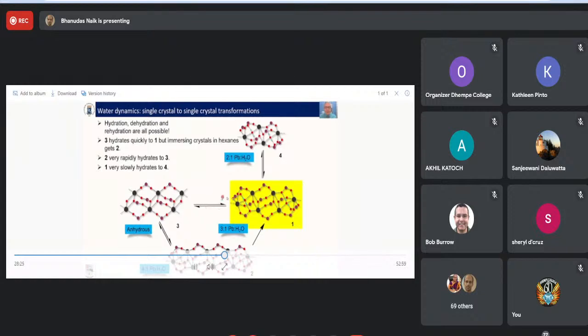In this compound, you can dehydrate 3 and you get the anhydrous compound. And if you're really, really careful when you hydrate it, you can manage to get crystals of this compound. So this is a single crystal transformation. We have a single crystal, we put it in a humid environment, we get 4. We can also heat it up on the diffractometer. The diffractometer has a cold stream which you can heat up to 400 Kelvin, so you can dry it out on the cold stream to measure this.